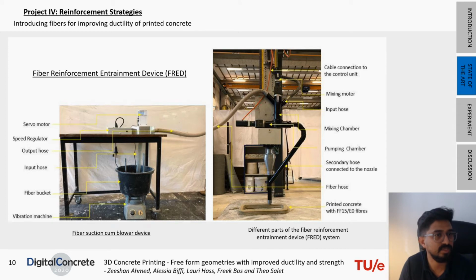The final project is on introducing fibers for improving ductility of printed concrete, for which a fiber reinforcement entrainment device was developed. The goal of this device is to introduce fibers into the printed concrete, and this device is in two parts. First is a fiber suction cum blower device, where the fibers are first added manually into the fiber bucket, and through the suction system, the fibers are transported into the mixing chamber of the FRED system. In the mixing chamber, the concrete from the concrete pump gets mixed using a motor and a mixing blade, and finally, using another motor attached to an Archimedes screw, the final pumping of the concrete is done, where the concrete comes out of a nozzle.